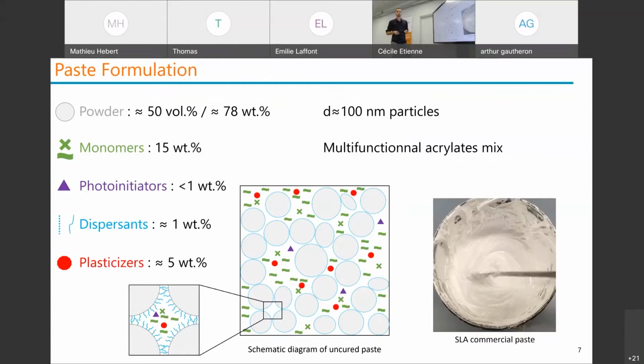So I talked about the ceramic paste. You can see how it behaves here, but you also need to know what is in this paste. The powder is the ceramic powder. It makes half of the volume, as I said, and it has very thin particles in order to have small grains and good mechanical performances. I also have monomers. Here it is a multifunctional acrylates mix. So I have different functionalities in order to get a great mechanical strength with not too many constraints, but in order to make it stand before the debinding.